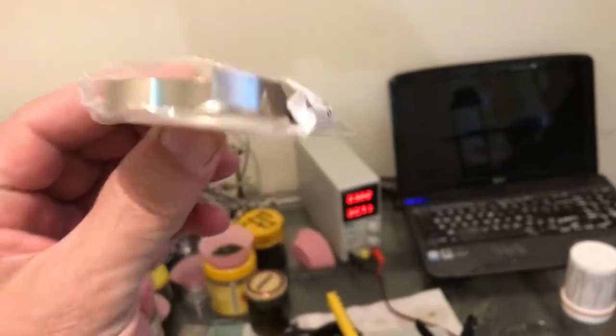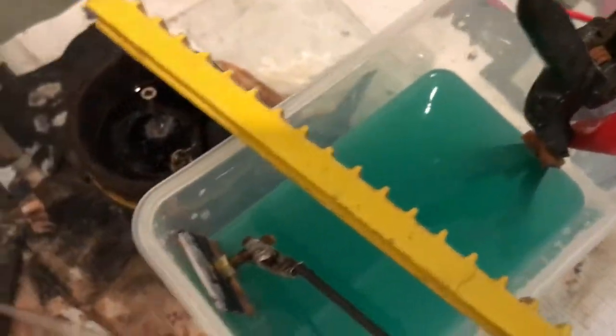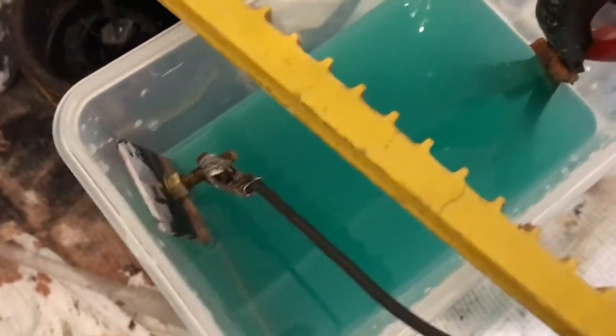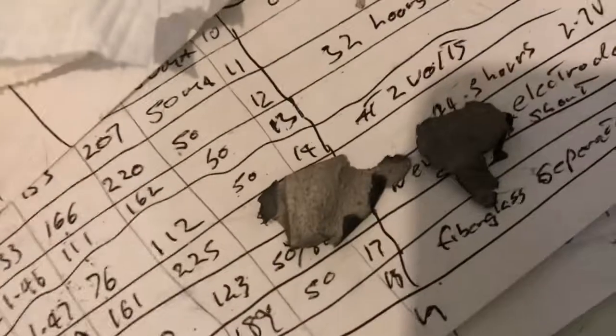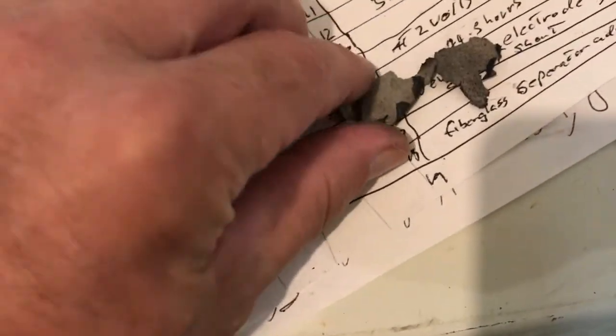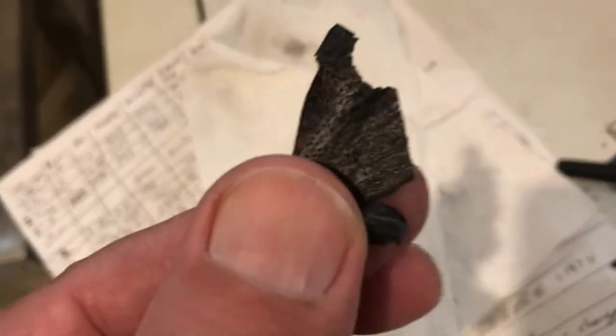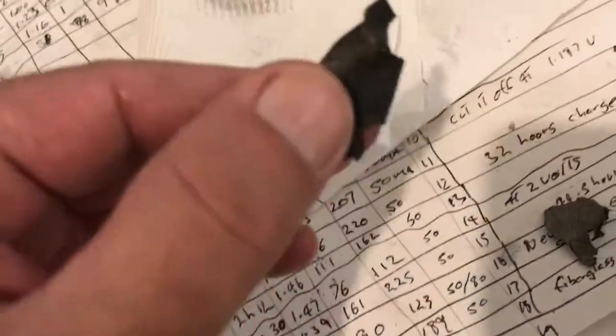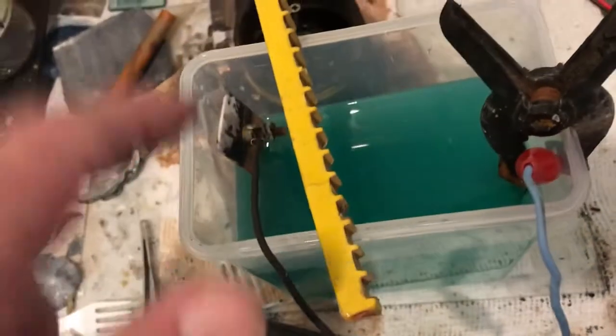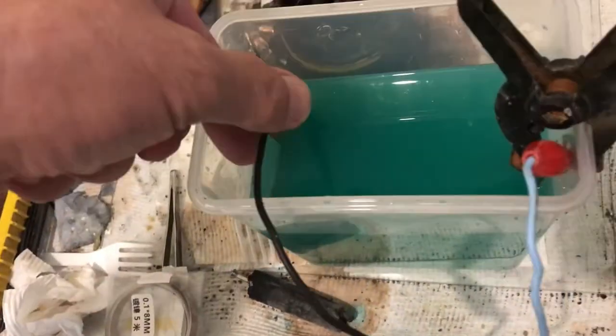I coated it in ink and then I nickel plated it with the nickel tabs you buy for lithium ion batteries. I've got some in nickel ammonia nickel sulfate plating right now. I first plated it straight under the carbon, and it was looking all good, but once it dried it sheared the carbon, so the ink was on this side and the ink left onto the plastic, so it sheared off. I was going to grind it up, and I'm probably going to. After this is nickel plated, I copper plated it first, and hopefully the nickel, this has been in there for about 5 minutes.